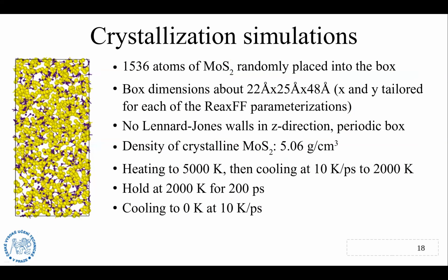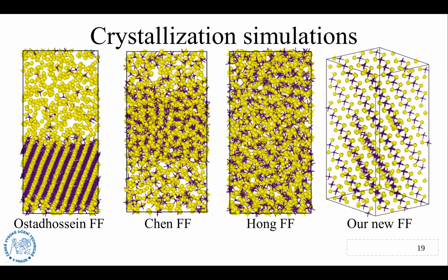So going further and not really trying to crystallize MoS2, just running basically a melt quench simulation with a little bit of hold at 2000 Kelvin. So again, box dimensions tailored to make layers properly in plane, like here on the right picture. Density of crystalline MoS2. Yeah, cooling at, well, in terms of simulations, relatively slowly, 10 Kelvin per picosecond. Of course, in real life, it's very hard to achieve. So the outcomes, again, state-of-the-art force fields either produce the wrong crystals or just produce amorphous structures. My new force field produces layered MoS2.